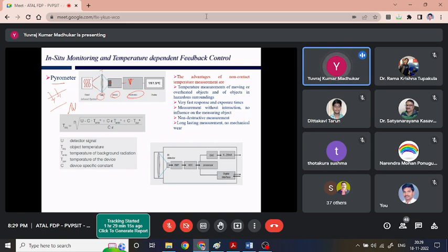However, it has been explicitly designed for a certain wavelength only. We can tune it; there are certain filters which allow only certain wavelengths to pass through and fall onto the sensor. It works on the principle of black body radiation. This is the formula by which we can calculate the temperature of a surface. Since we are using certain optics, we can focus them onto a very small area, of the order of nearly 0.1 mm, 0.2 mm, 0.3 mm. Nowadays we can focus it to such a small diameter, no problem.